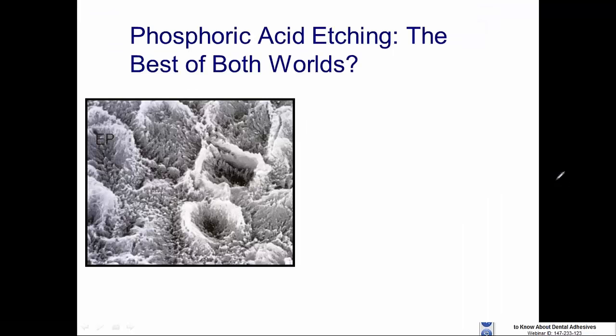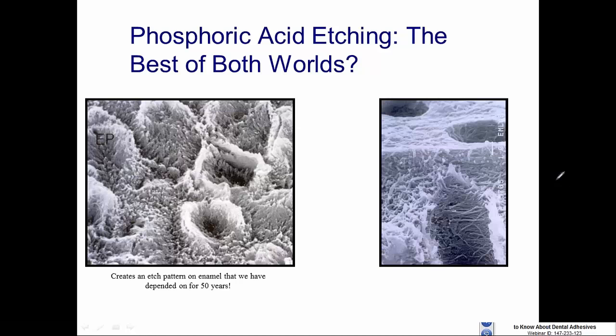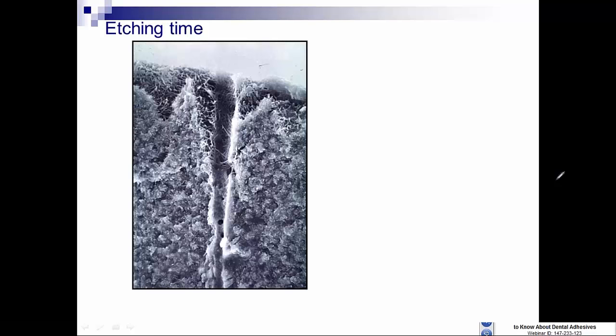So is phosphoric acid conditioning the best of both worlds? Enamel, the most durable, reliable, micromechanical bond. Dentin, if we do not collapse the collagen, we interpenetrate the resin monomers, we remove the smear layer, and allow infiltration of these primers. So one of the critical parameters if we're using an etching, rinsing dentin technique is the time. All manufacturers recommend etching enamel for no less than 15 seconds and dentin for no more than 15 seconds.